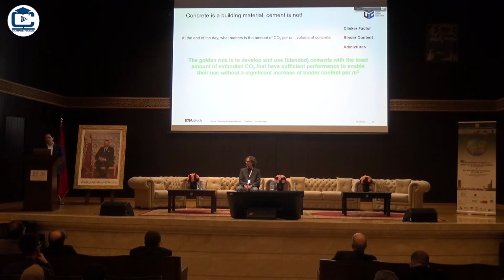So to me, the golden rule is that we need to develop cement, blended of course, with the least amount of embodied CO2, but that have sufficient performance to enable their use without significant increase of the binder content per cubic meter. And this, I think, is what distinguishes LC3 from other blended cements, that it allows me to translate the CO2 saving from the bag of cement to the cubic meter of concrete very efficiently.